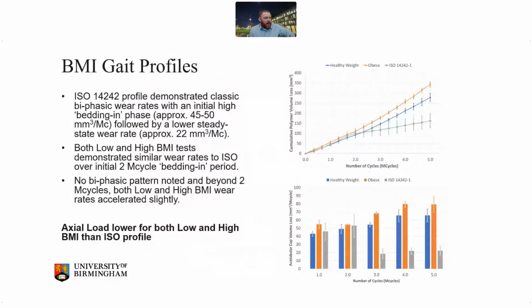When we compare the wear rates to an ISO profile, this is the ISO data that I presented earlier on that slide. So we had this bedding-in phase, and then a steady state wear rate. What we noticed with the BMI data was, although the loads on both were ultimately lower, there wasn't this clear bedding-in phase, and actually we just started off with a much higher steady state wear rate. So after 5 million cycles, the wear was higher for the physiological gait, which is the key point to take away from that: despite the loads being lower, the wear was higher.